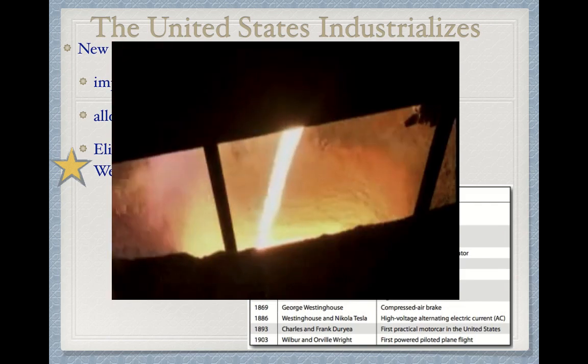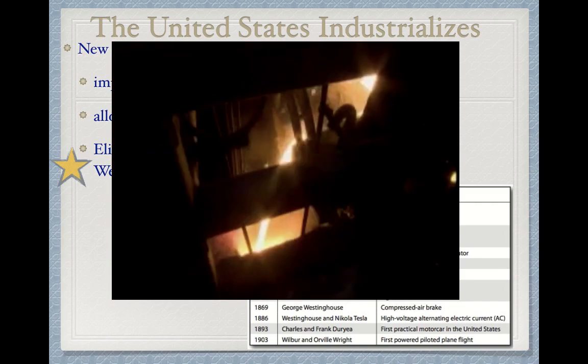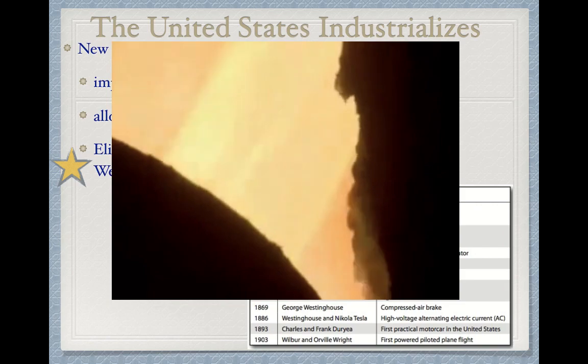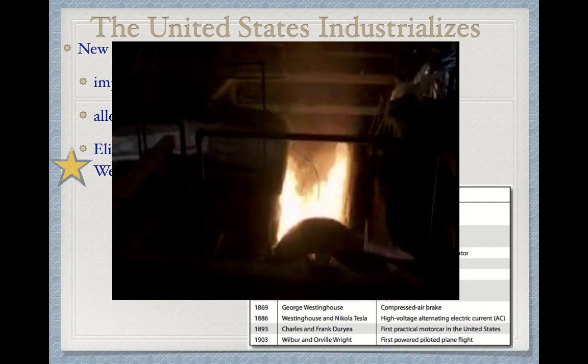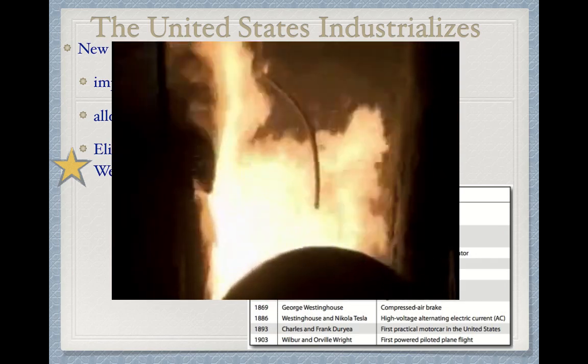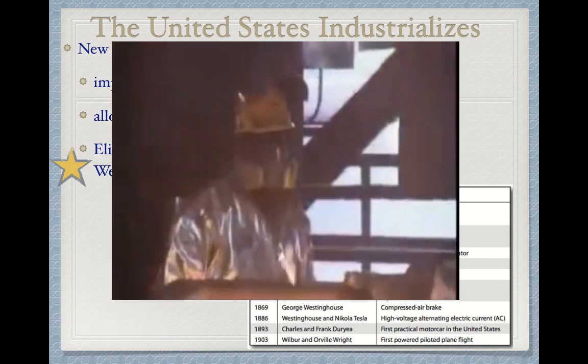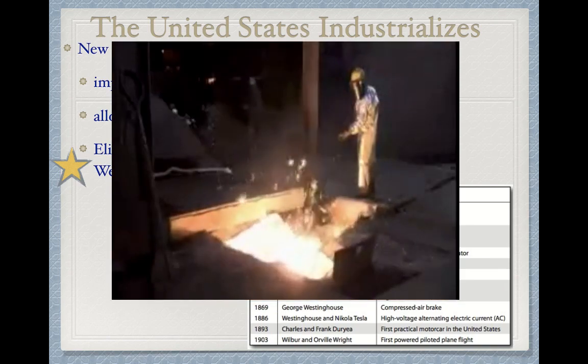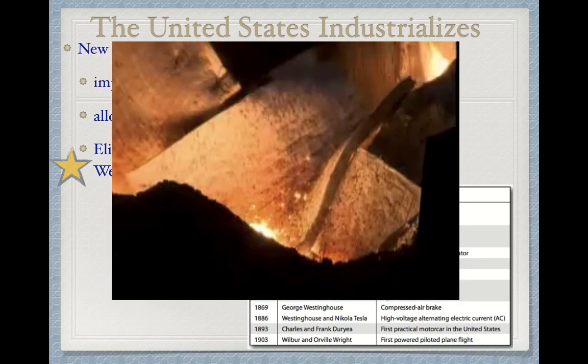It's called pig iron because it was originally cast into molds resembling piglets suckling a sow. But ironically, though the iron has been freed from the oxygen, the molten pig iron that flows from the furnace has a new problem: too much carbon. Over 4%, which makes the resulting metal much too brittle. To become steel, that number needs to be reduced to less than 2%.